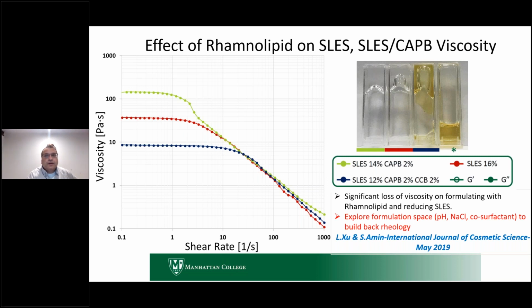So you have dropped viscosity considerably, and you can see in the sample pictures that the yellowish-tinged colors are much more liquid-like. This changeover is happening because you are changing the microstructure of the system. And as I said, I'm not going to go into the details of the study here, but this was just an example of what is happening when I do a very simple substitution, right?